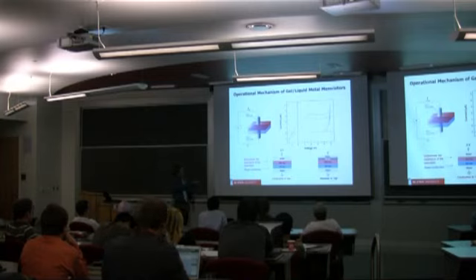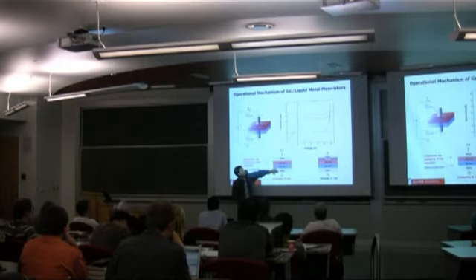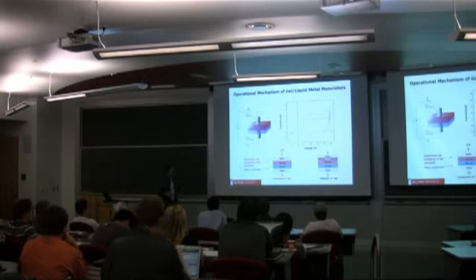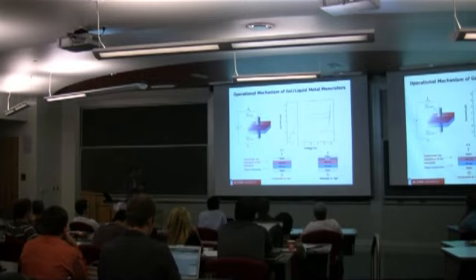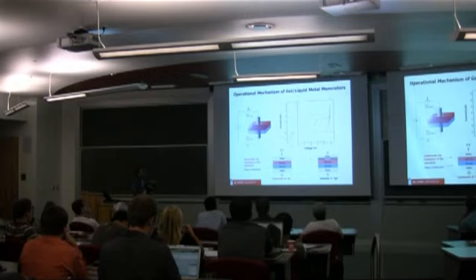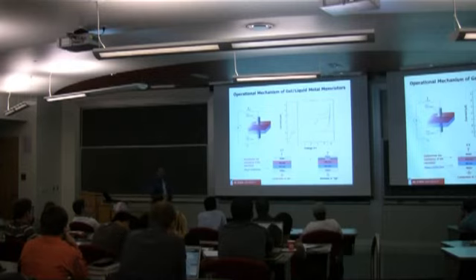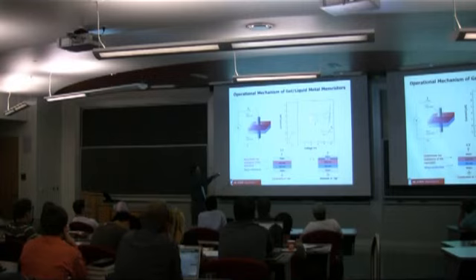This is a cross-sectional view of our device. We've got metal, acid gel, base gel, metal. And when you start out, you've got a very conductive pathway. You've got metal basically in contact with salt water. And so you start here, of course, at 0 volts and 0 current, and you start to sweep the voltage. And as you do it, you get a current. That's this scan here. So it's conductive. But in doing so, you start growing an oxide layer. And when you form that oxide layer, it becomes resistive. So now when you scan in the other direction, it's no longer conductive, it's now turned off. So we now have two states: conductive, resistive, on, off.